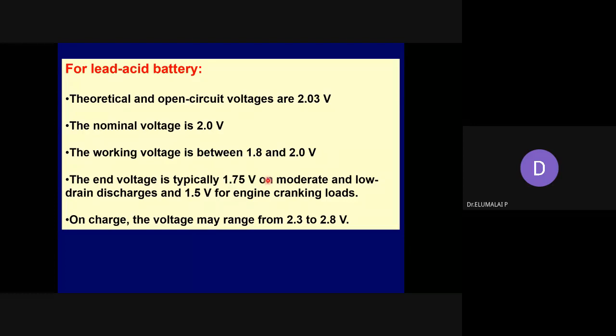So maybe in the case of an SLI battery or traction battery, you can go a little bit lower than 1.8 volts. In any case, not less than 1.5 volts. Not in any case less than 1.5 volts. So during the charging, the battery can be charged up to 2.8 volts. This is the characteristic you should be remembering. This is for a single battery.